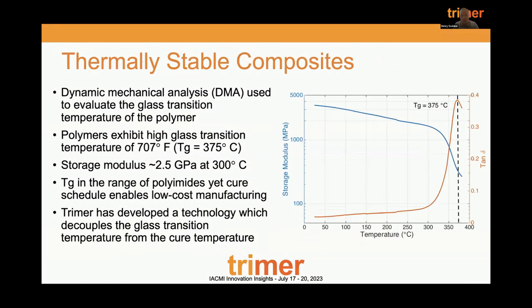This plot is just showing some of the thermal stability that I mentioned. So glass transition temperatures can be extremely high. These can be done with a fairly simple post cure here. And we do have a new supersonic wind tunnel blade that's going to be utilizing our resin system. That's a 450F continuous use temperature and a 20-year fatigue life application. So really we can do some very good thermal performance as well. And this could be just a standard system. And also we do have some more aerospace level performance that performs a little better out of the die than you might see in some of our infrastructure materials.